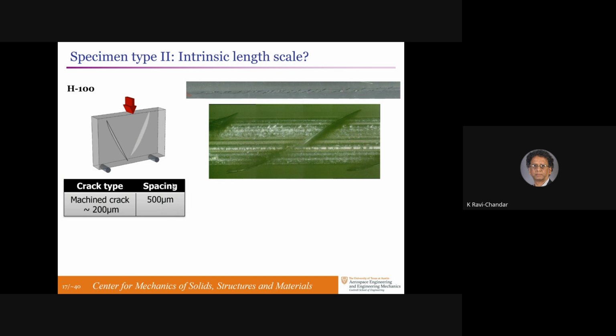So we took the same specimen, inverted the 3-point bend configuration. Now these cracks are under predominant compression and shear. So the compression will prevent the cracks from running away. The shear will make them grow. And so we could have cracks that pop and stop at some point, so we could look at the geometry of that. And I'm only going to show you pictures of what the eventual outcome is.